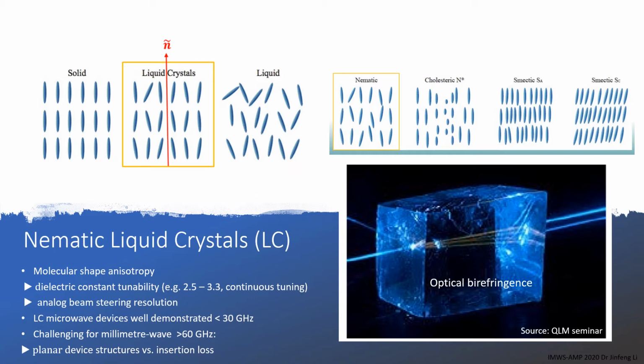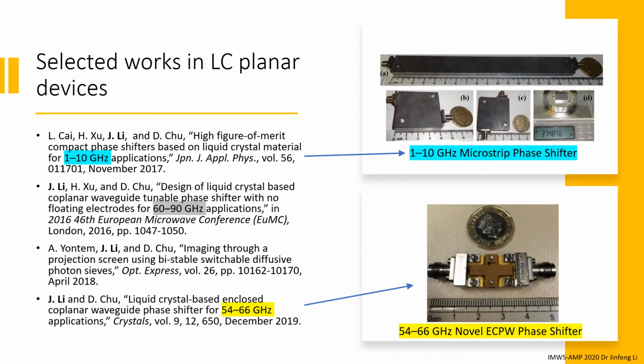With a decrease of the wavelength from microwave to millimeter wave, device performance degradation less observable at the microwave can be noticeable in the millimeter wave. To our knowledge, high insertion loss at millimeter wave remains the key challenge of liquid crystal planar phase shifters when comparing with the competing waveguide technologies. In my previous work in tunable delay line phase shifters based on highly anisotropic liquid crystal as tunable dielectrics, I have pushed the limit of the planar microwave transmission line implementation from the 10 GHz microstrip to 60 GHz enclosed coplanar waveguide, and progressively towards 90 GHz high aspect ratio coplanar waveguide that can challenge the current status of manufacturing in terms of electrode patterning and the liquid crystal alignment.